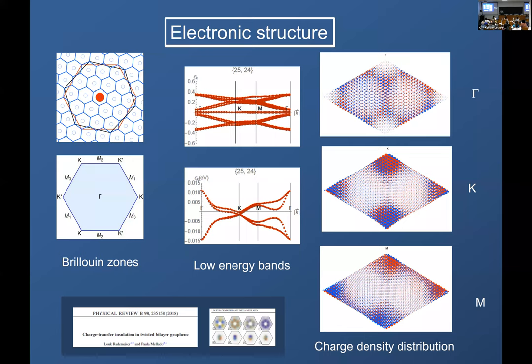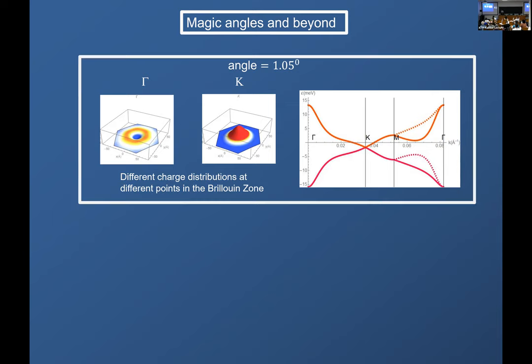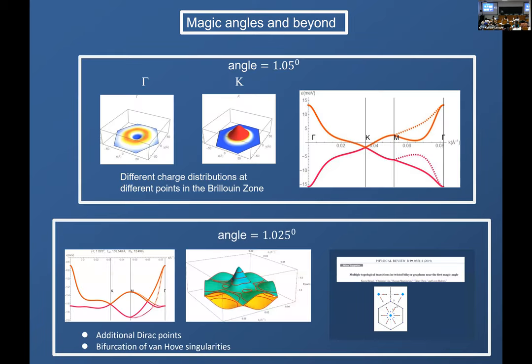The wave functions of the associated states are totally different. At the K point, these wave functions are piled at the AA regions, as Ali mentioned before, while at the gamma point, the wave functions are totally different. They spread out more or less uniformly over the entire real space unit cell. This is again another picture of the charge density of different points in the same flat band. I emphasize this thing doesn't happen in a typical flat band strongly correlated system.